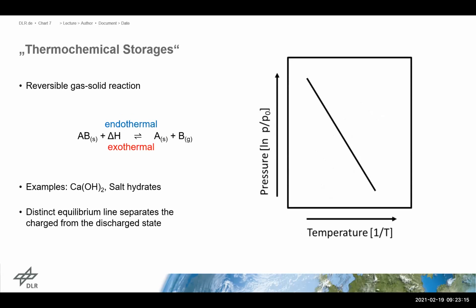This is a bit different if we talk about chemical reactions, in this case gas-solid reactions. The reaction equation here, generic, can be the same. The difference is that now this solid material A undergoes structural changes. It's a chemical reaction. A new compound is formed. This could be, for instance, the case for calcium hydroxide. If you add thermal energy to calcium hydroxide at about 500 degrees Celsius, this is what you need, you dissociate it to calcium oxide, a new chemical compound, and water vapor. And in this case, the diagram on the right side looks a bit different.